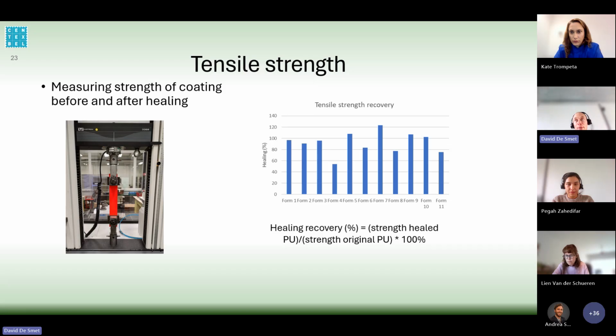So actually, this is measuring the strength of the coating before making a scratch, and then after making a scratch and healing it. So then by just comparing the tensile strength before and after the healing process, you can have an idea about healing efficiency. By doing the ratio of the two and multiplying by 100%, you have a healing recovery percentage.